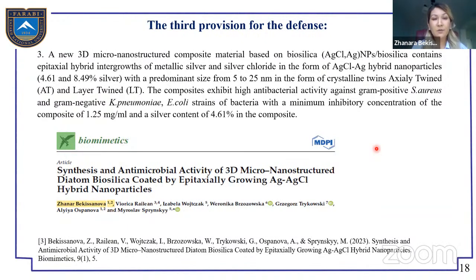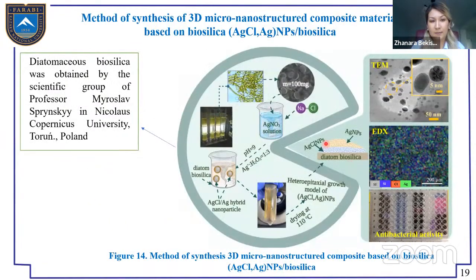The provision for defense was published in the article in Biomimetics and can be confirmed with the following results. The diatomaceous biosilica was obtained by the scientific group of Professor Miroslav Sprynskyy at Nicolaus Copernicus University. The setup of growing and purifying the diatom biosilica, and the experimental part of obtaining the composite, contain two stages: impregnation of diatomaceous biosilica with silver nitrate solution, artificially adding sodium chloride, basifying and reducing with hydrogen peroxide, and obtaining hybrid silver chloride and metallic silver nanoparticles, which were investigated with physicochemical analysis.